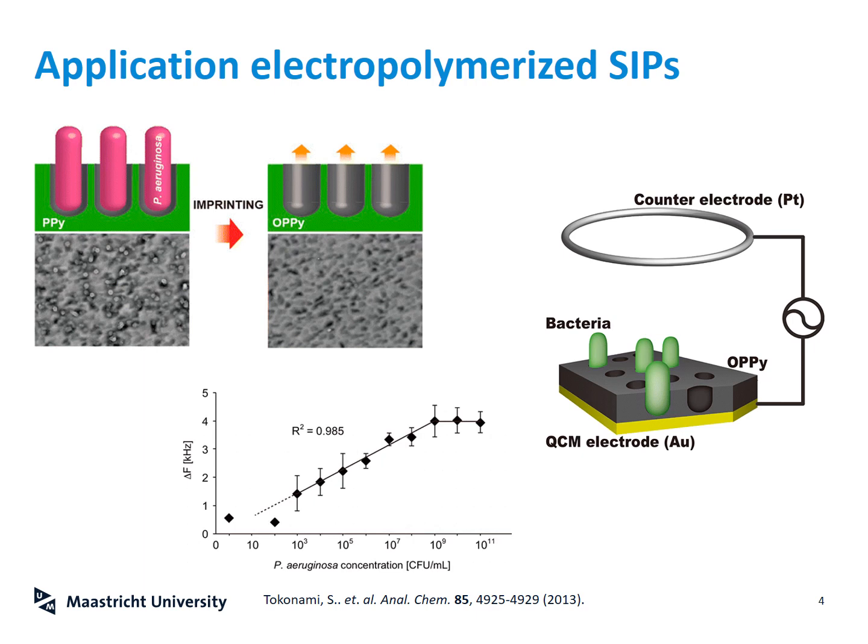this effect will become bigger as the concentration of bacteria becomes bigger until you have about a billion bacteria per milliliter. If you increase the concentration even more after that, nothing will happen anymore. This is because all of the binding cavities have been filled with bacteria, and adding additional bacteria won't result in more bacteria binding to the surface and also no change in signal.